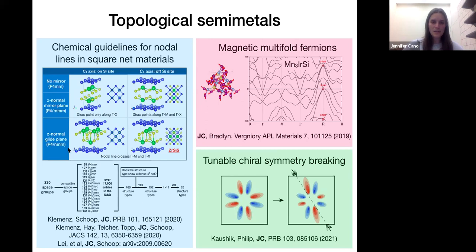And then we did this little algorithm here on the bottom of the slide. Basically, what we're trying to do, this is actually a cool idea that I should give credit to Leslie for, is if you have stacked square nets, you can identify a spacing between layers and a spacing between atoms in the layer. And that gives you a ratio of two atomic spacings. And if the spacing between atoms is bigger than the in-plane spacing, you can treat it as a 2D material. So that gave us a tolerance factor.